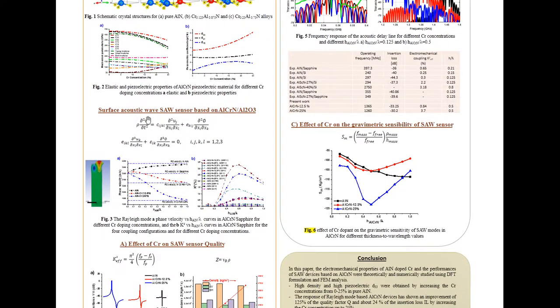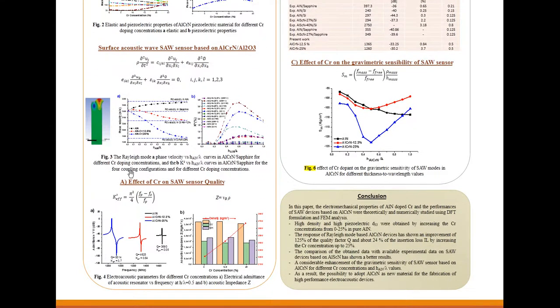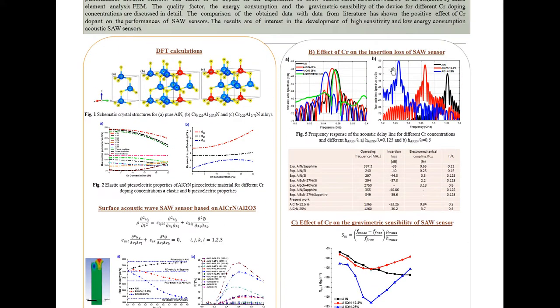Starting from the Newton law in piezoelectric medium and using finite element analysis, the characteristics of surface acoustic wave in aluminum nitride deposited on sapphire could be studied, and the study revealed a considerable enhancement of SAW sensor characteristics, such as the high electromechanical coupling factor and high quality factor, low insertion loss, which allow the realization of low energy consumption acoustic sensors,